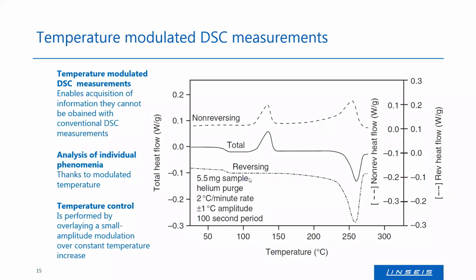So this is the reversing and non-reversing part of our measurement. So here in the mid of this diagram, you can see the total heat flow of, for example, PET. I think it's PET here. So we can see the glass transition at around about 80 degrees, the recrystallization at around about 130 till 150, and the melting at around about 250 degrees. And now we can split this signal to the reversing heat flow at the bottom and the non-reversing heat flow at the top here in this diagram.